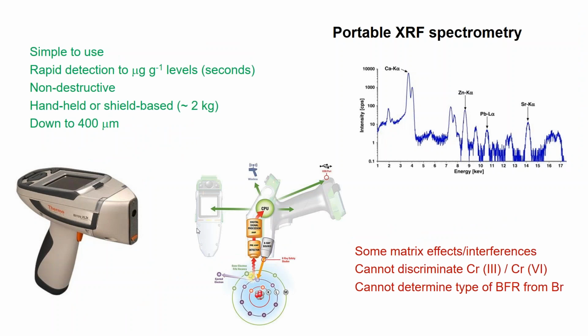Just to briefly outline the principles, portable X-ray fluorescence is ideal for this, and it has been used by various industries where there are regulations on plastic composition. Simple to use, you can detect elements down to microgram per gram levels in a matter of seconds, and we've tried it on microplastics. You can get down to about 400 micrometers in size before you lose your precision and accuracy. Very simple technique. An X-ray beam is fired at the sample, and secondary X-rays are given off which are characteristic of different elements. So from the spectrum we can work out what's there, and with certain software we can convert these to concentrations. The only problem with this technique is it does have some interferences, matrix interferences in some plastics, and it can't discriminate between species or oxidation states.